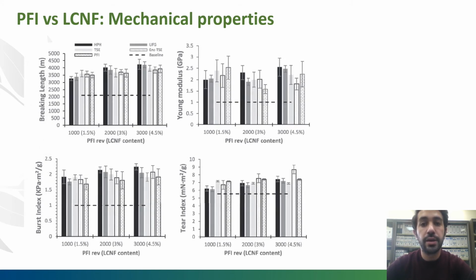The different lignocellulose nanofibers were applied as reinforcement in recycled paperboard and compared with the reinforcing effect produced by mechanical refining as conventional treatment. In general, the mechanical properties increase as the lignocellulose nanofiber content and the intensity of the mechanical refining increase compared to the baseline values of the recycled carton. Setting a target value of 3,443 meters for the reinforcing effect, data that were obtained from the analysis of virgin cardboard at industrial level, we can see that this value is reached for 1.5% of lignocellulose nanofiber and 3,000 revolutions for mechanical refining, with the same effect on the reinforcing effect for the different treatments.